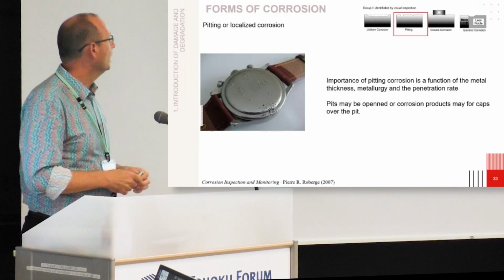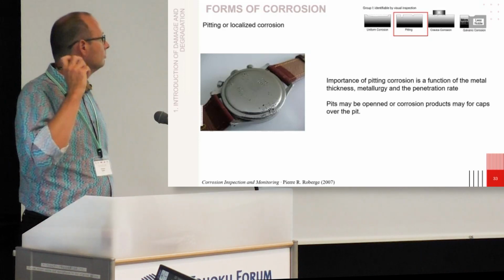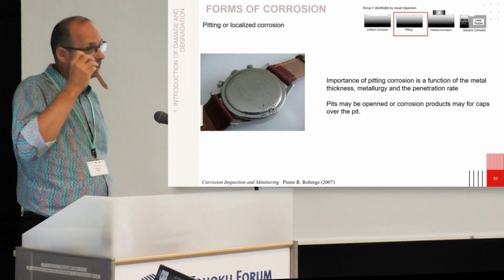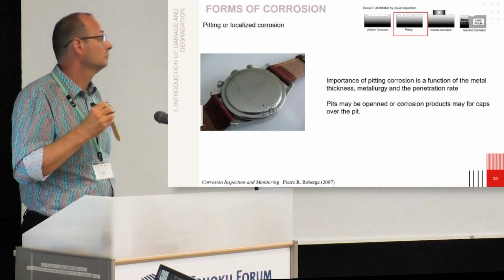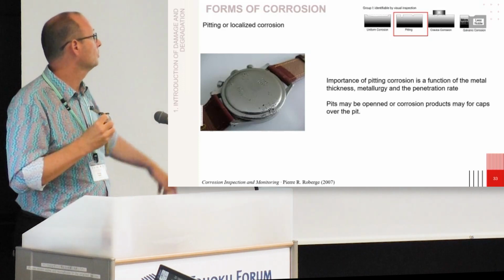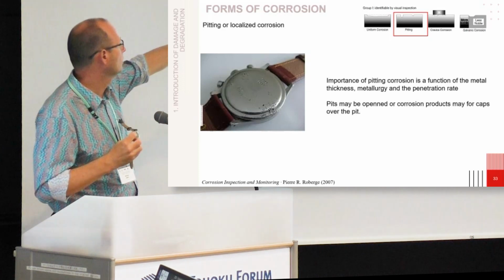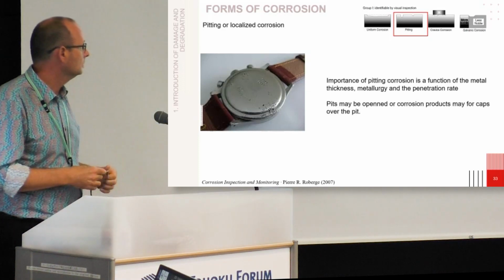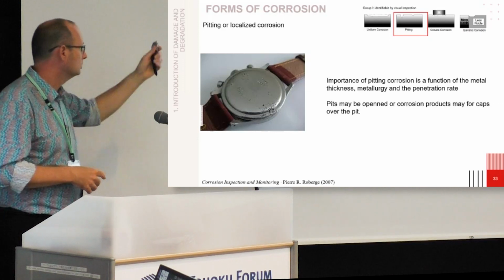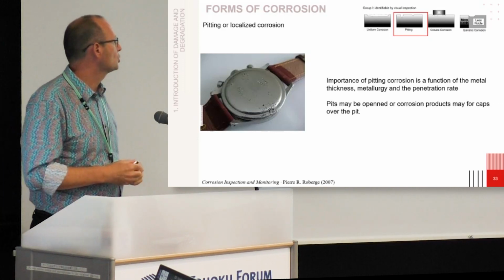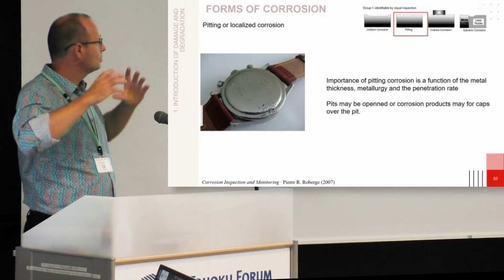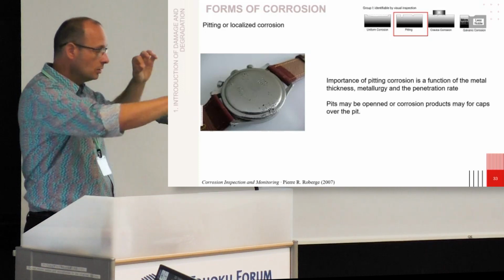And here, even if for me it's stainless steel, stainless steel is quite sensitive to pitting if there is any chloride environment, so Cl minus. And here you will have such kind of degradation for a long-term exposure. So you can see here, not all the structure has been damaged, it's locally damaged.